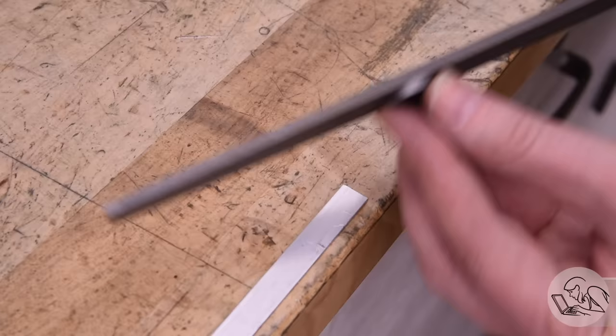Another way to do this test is to rub it back and forth on the file. And if it feels the same, sliding in both directions, then the file isn't cutting it. To sell you that point on brittleness, here's another piece of drill rod that I hardened to 65 Rockwell C. And boom, look at that. You can shatter it just by tapping it with a hammer. And look how clean that break is.